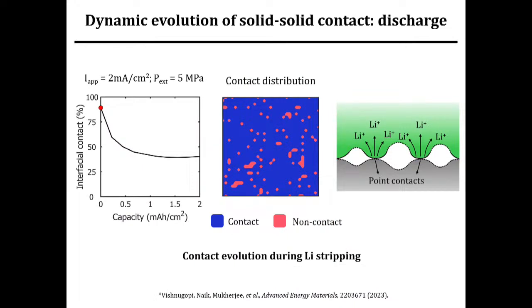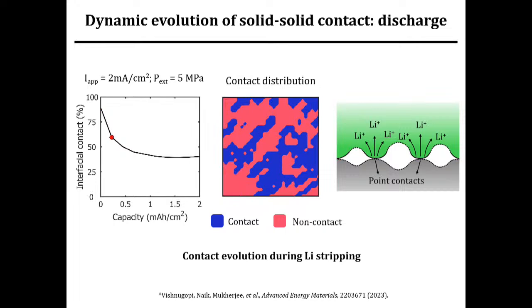Most of the challenges I've talked about till now relate to the plating or charging of the solid-state battery. However, solid-state batteries have a unique limitation when it comes to stripping. In principle, with every lithium metal stripped at the solid electrolyte and metal interface, you need lithium to replenish these physical gaps or voids that get generated. There are mechanisms such as the mechanical deformation of lithium, known as creep deformation, and the diffusion of lithium that can fill these gaps. The key question is whether these intrinsic diffusion rates can compete with the rate at which metal is stripped from the lithium and solid electrolyte interface.